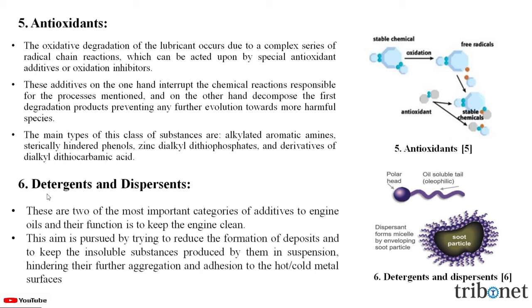The fifth one is detergents and dispersants. These are two of the most important categories of additives to engine oils and their function is to keep the engine clean. This aim is pursued by trying to reduce the formation of deposits and to keep the insoluble substances produced by them in suspension, hindering their further aggregation and adhesion to the hot or cold metal surfaces.